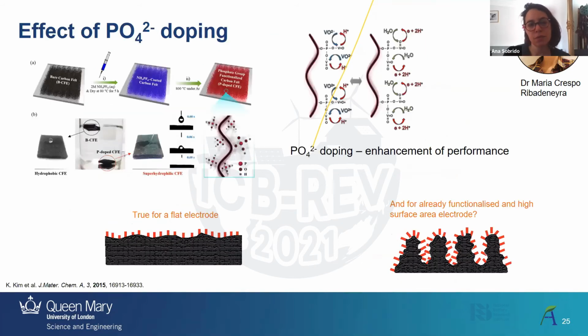So we also wanted to have a look at the effect of other functional groups at the surface. It's already been reported that using phosphate functional groups at the surface of carbon felts leads to an enhancement of the performance. As you can see here in this diagram, it seems like because you have free oxygens available to react with the vanadium, that is going to multiply, if you like, the number of sites that the vanadium has to react compared to just one OH.